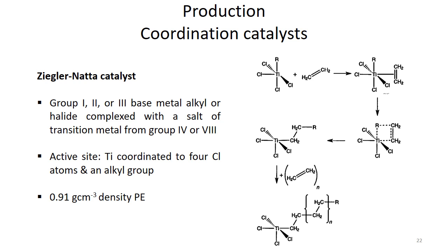In most of the Ziegler catalysts, there may be one or more active sites present. The active site consists of a titanium atom coordinated with 4 chlorine atoms and an alkyl group, which are arranged octahedrally to leave a vacant site. What happens is that an ethylene molecule attaches itself to the vacant site and is inserted between the metal atom and an alkyl group via a transition complex. In this process, a new vacancy is created.